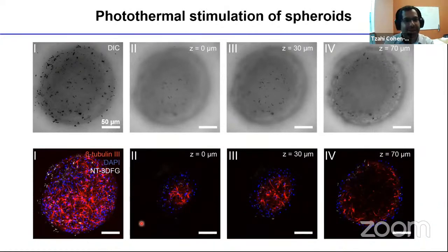And we used the same spheroid and selected one cell within the spheroid and used a laser pulse and showed that we can stimulate the whole network while doing so.